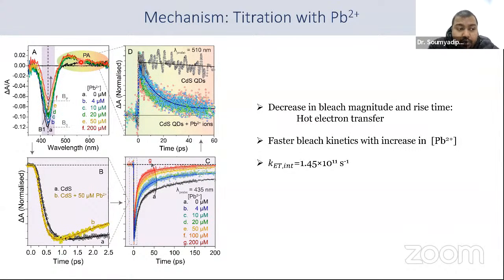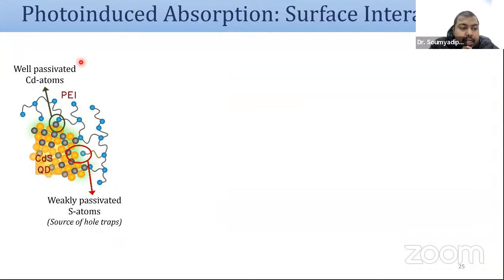Now, what is the Stark effect? In presence of light, the electron in the conduction band goes to a lower energy level and the hole goes to a higher energy level, and therefore a charge separation comes up. And there's a charge separation due to the presence of lead 2+. So based on this observation, we can propose a mechanism that PL quenching is due to purely surface interaction.